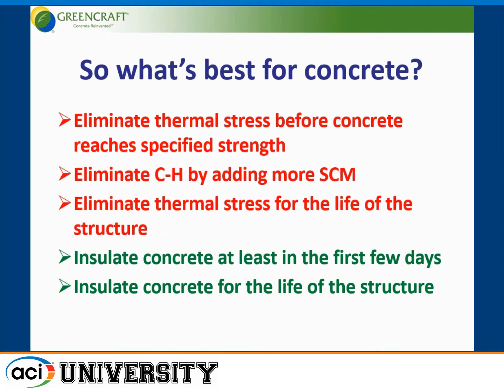So at the end, what's best for concrete? To sum it all up, we need to eliminate the thermal stresses before the concrete reaches specified strength, eliminate the calcium hydroxide by adding more supplementary cementitious materials, and if we can eliminate the thermal stresses for the life of the structure, that's even better. So how do we do that? We insulate the concrete at least in the first few days until it reaches specified strength, and if possible, insulate the concrete for the life of the structure.